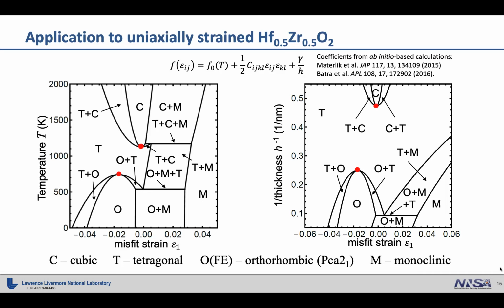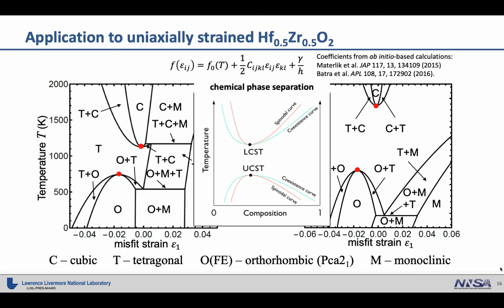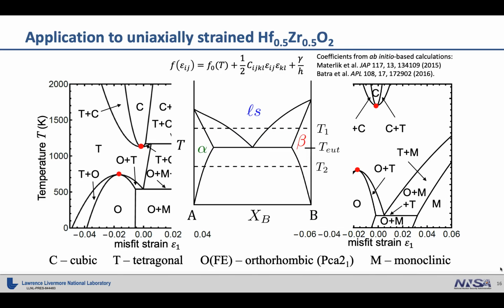We have some qualitative observations. The first is that slightly tensile strain or slightly compressive strain can favor the orthorhombic, ferroelectric phase. Also, at very thin film thickness, the cubic phase will be dominant because of the small surface energy of the high-symmetry cubic phase compared to the other low-symmetry phases. And there are some interesting observations about the topology of these phase diagrams, such as the critical point, which is akin to chemical phase separation. And this eutectic-like shape is also reminiscent of the chemical phase diagrams for eutectic binary systems.